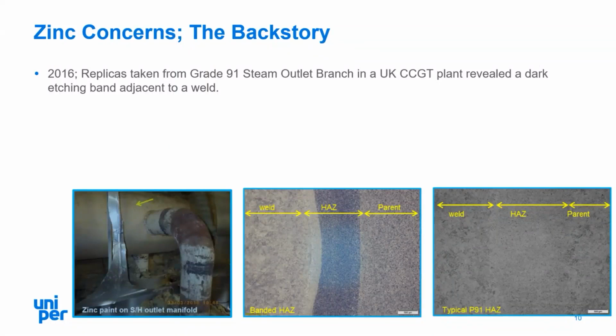The tentative steps taken towards identifying the problem were made in 2016. Colleagues at Technology Centre were involved with the routine integrity assessment of a grade 91 steam outlet branch, and this revealed a dark etching band adjacent to a weld, as shown in the central of the 3 images down the bottom. This was within the outer heat affected zone adjacent to the parent and slightly remote from the fusion boundary.